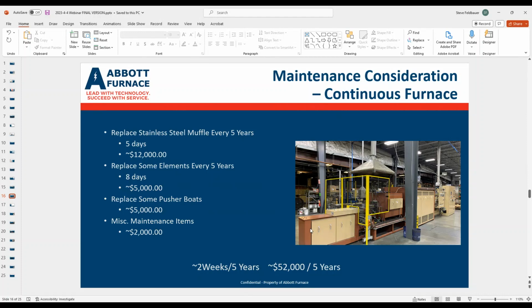In this case, you'd replace the stainless steel muffle every 5 years, because remember, now we're going to use that stainless steel muffle in that debind area, okay? And so it's a lower temperature. We're going to be somewhere between 500 to 650 degrees C. So the muffles last a long time. 5 years is actually pretty conservative, to be honest, in that temperature range. But let's just say we're going to replace it anyway. It's going to take about 5 days, and the muffle's going to cost you about $12,000.